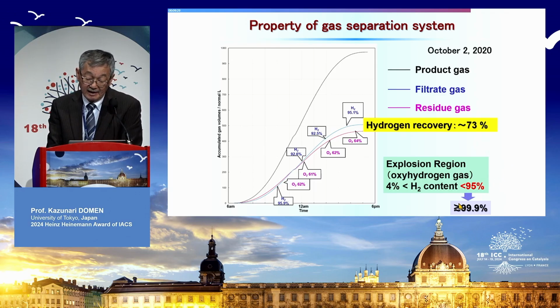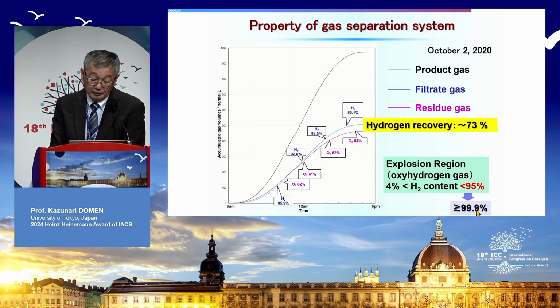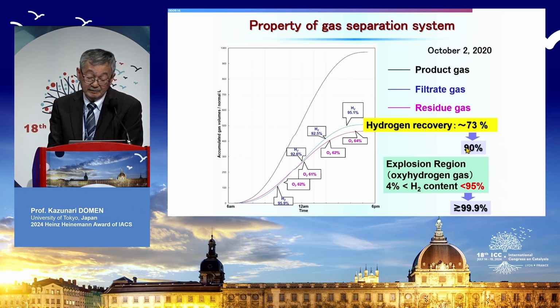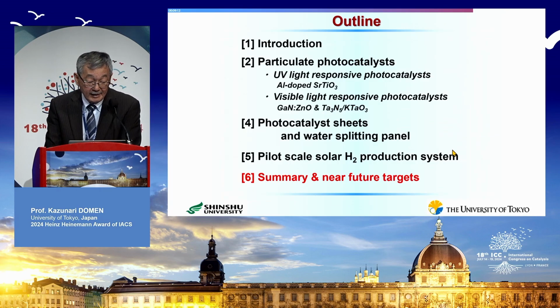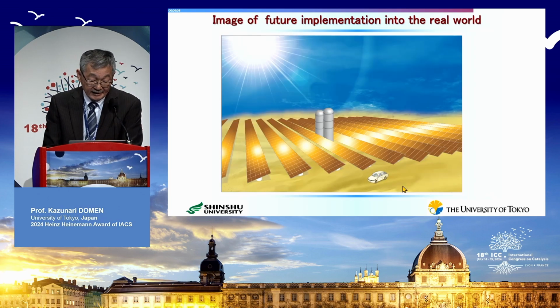And by quenching contamination of oxygen, we can get more than 99.9% purity. Also, the hydrogen recovery is now being improved to 90%, but we would like to achieve 95 to 98% of hydrogen recovery. Now let me summarize and discuss a little bit more about near future targets.